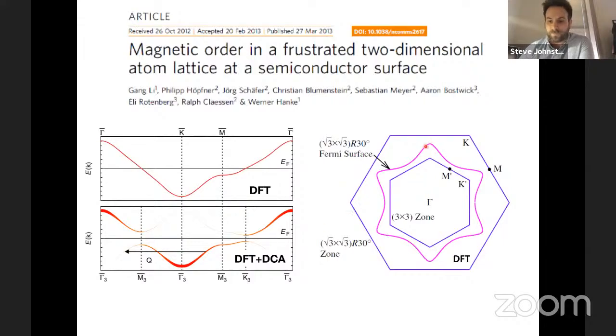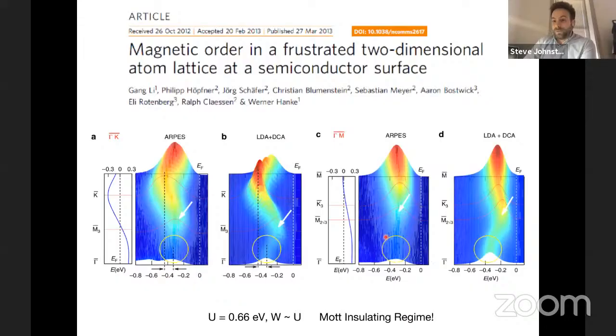And just for reference, this is what the Fermi surface looks like for the undoped system in DFT. I'll come back to this a little bit later. So in this paper, they then went and compared against ARPES measurements. So this is what's shown here. So A and C, these correspond to actual ARPES measurements along certain high symmetry cuts. And you can see, again, what looks like a very broad, weakly dispersive band that's got a gap separated from the Fermi energy.